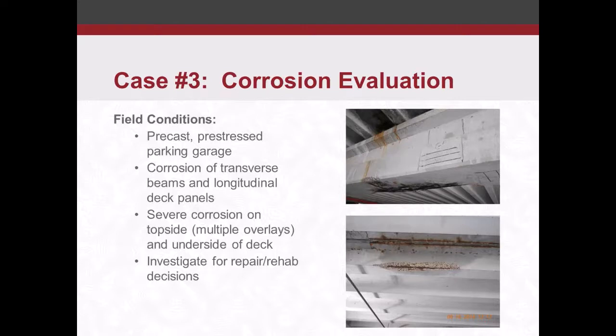So our next case, corrosion evaluation for field conditions. This is a precast, pre-stressed parking garage. We had corrosion of the transverse beams and longitudinal deck panels. This top photo shows one of the transverse beams. You can see some of the tendons exposed and even broken, from spalled concrete.